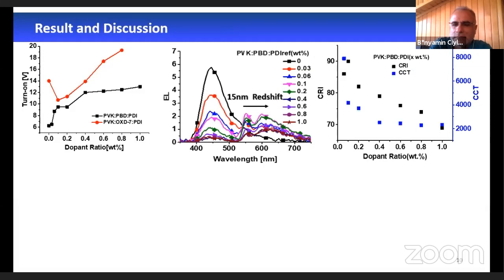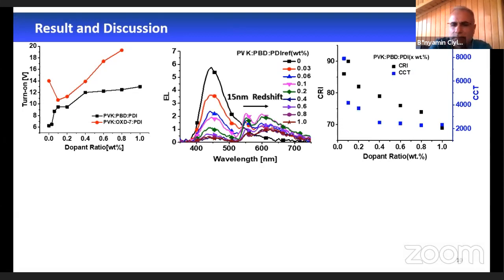Increasing the doping weight percent of PDI in the host matrix resulted in red-shifted electroluminescence spectra, and best white light properties were achieved with 0.1 weight% of PDI. As the PDI ratio increases, the electroluminescence from the red region becomes dominant, resulting in decreases in both CRI and CCT values. After fixing host matrix as PVK-PBD, green emitting material PTE was used instead of PDI.